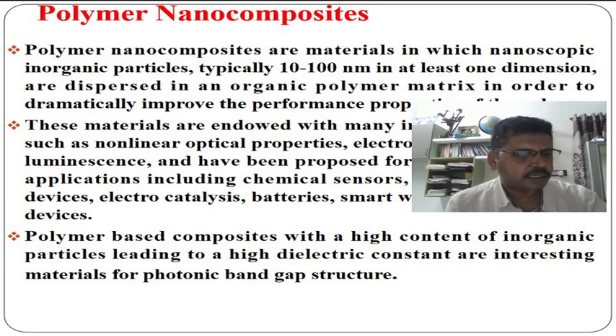On the other hand, the usage of ultrasonic irradiation is simple, green and low cost for the preparation of nanocomposites. With the usage of ultrasonic, extraordinary reaction conditions like activation of surface, high pressure and also temperature are created for a very short time in a liquid. It cannot be achieved by other methods such as mechanical or magnetic stirring. The mechanical mixing method is not as homogeneous as the ultrasonic method, and it does not give the desired dispersion.